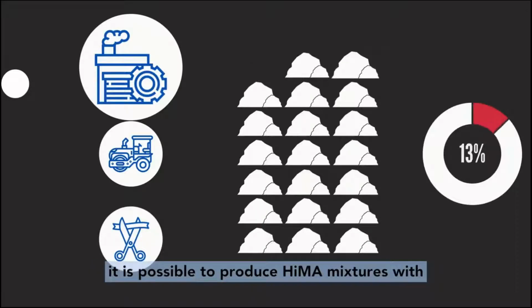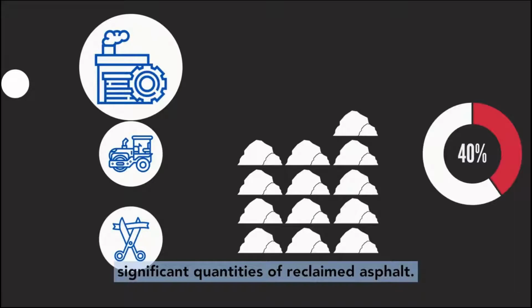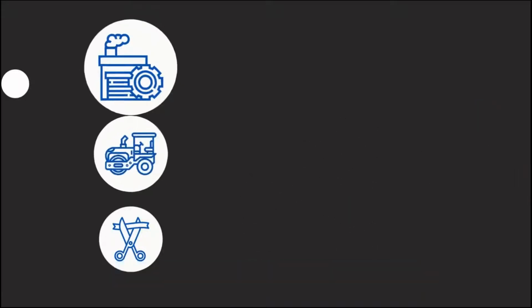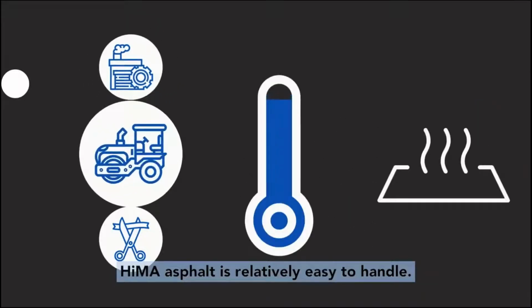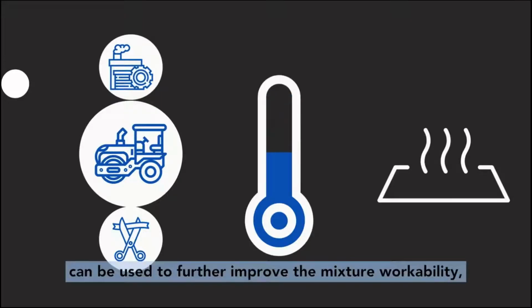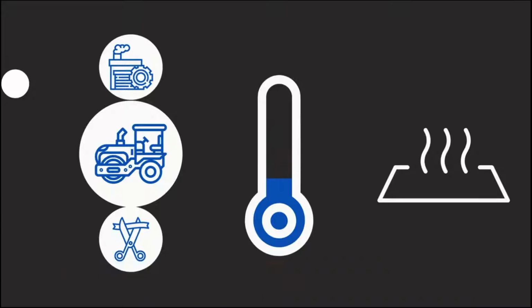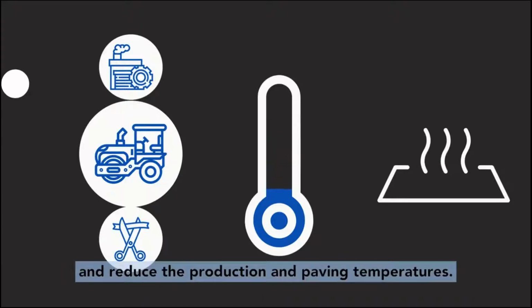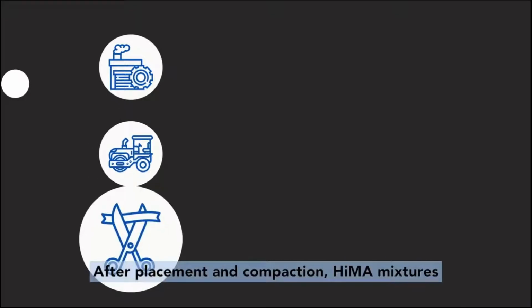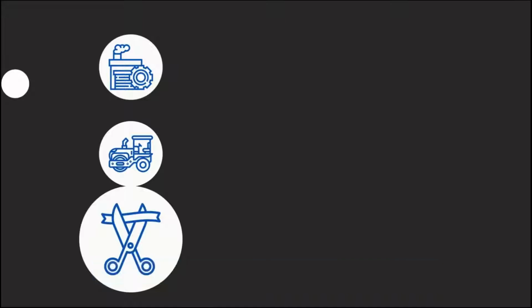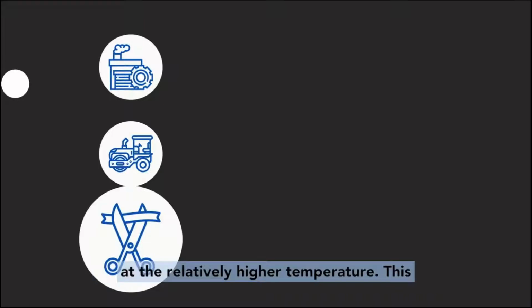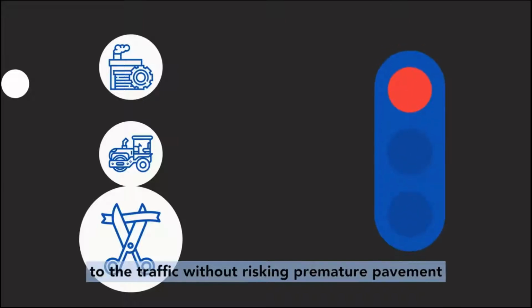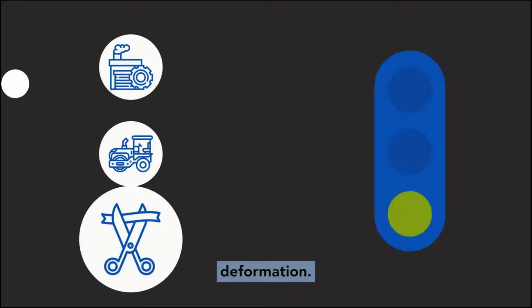Additionally, it is possible to produce HiMA mixtures with significant quantities of reclaimed asphalt. HiMA asphalt is relatively easy to handle. The conventional warm mix asphalt technologies can be used to further improve the mixture workability and reduce the production and paving temperatures. After placement and compaction, HiMA mixtures reach the conventional asphalt mixture stiffness at a relatively higher temperature. This characteristic may allow a faster opening to the traffic without risking premature pavement deformation.